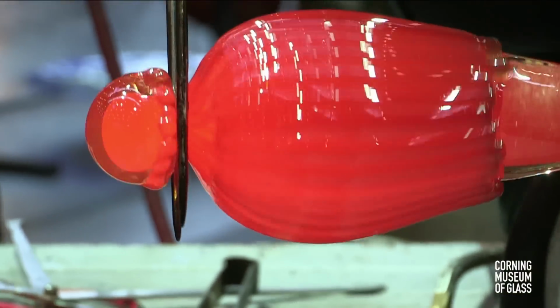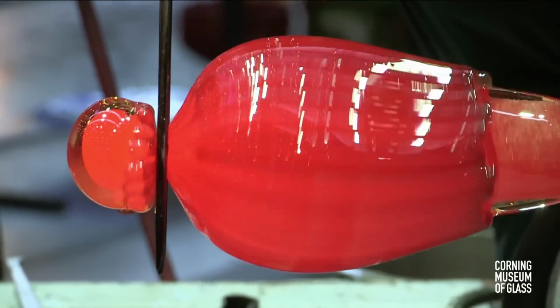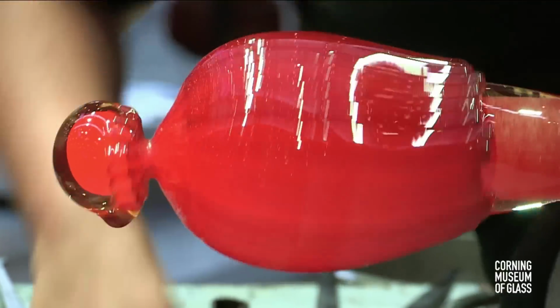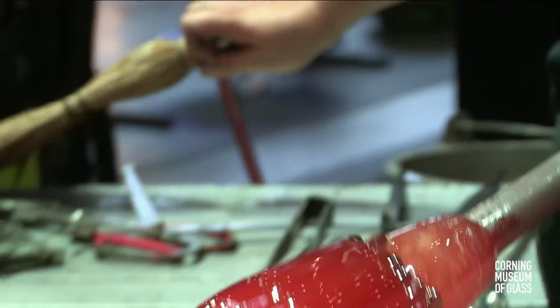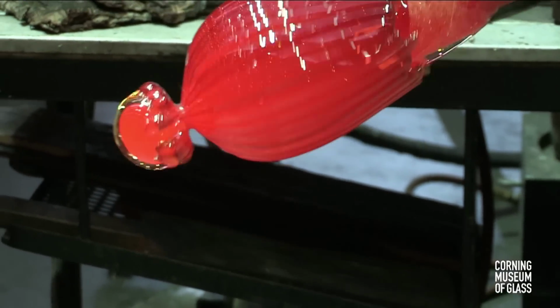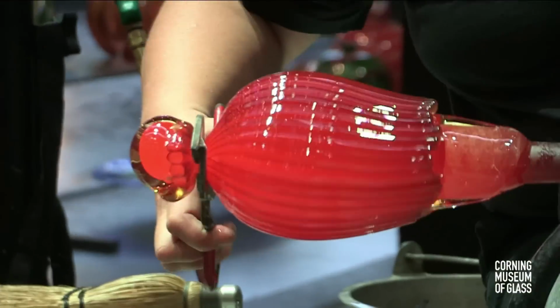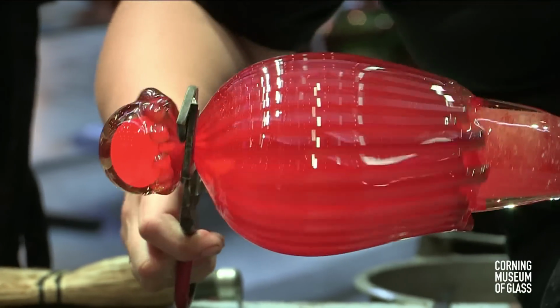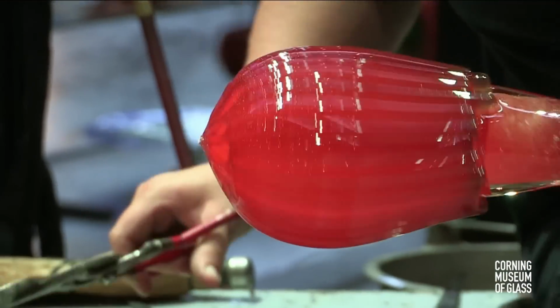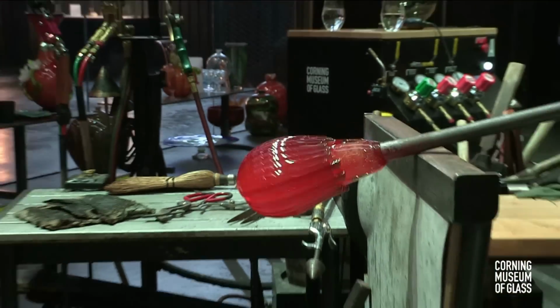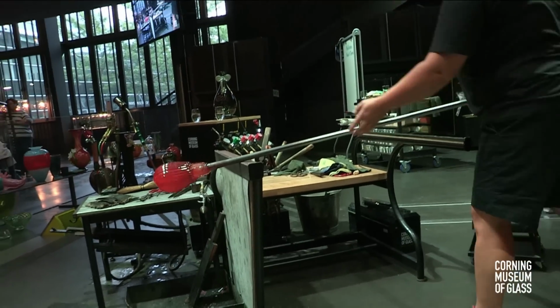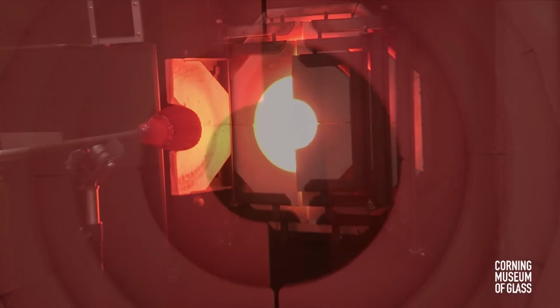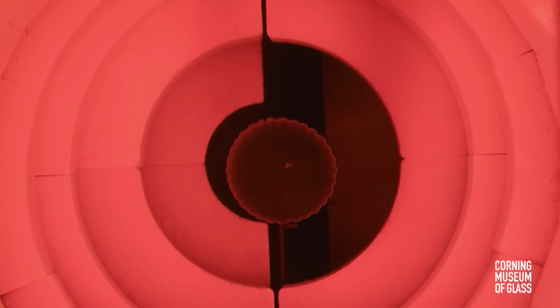Yeah, 2,100 degrees Fahrenheit, is that a critical temperature? I would say that's an important temperature because that's the temperature we have found that the glass works the best and for the longest, right? So we have a lot of heat when we come out of the furnace. We can use that initial heat to our benefit. One would argue that the more heat you use from your initial gather out of the furnace, the more shaping you get done with it, the better the glassmaker you are. So it really is all about efficiency. The more heat that you've used with that gather from the furnace, the more you can get done because the glass will never be that hot again.